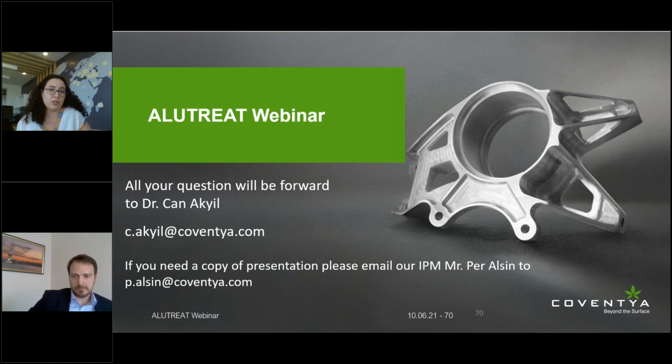Because of the porous structure we already mentioned, the oxide layer tends to absorb chemicals because of the capillary effect. So the oil, water, everything can be plugged in the oxide structure. That's why it feels sticky if we do not cover them up properly. So this is the reason behind the stickiness.